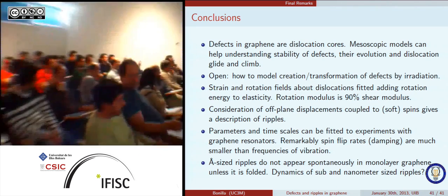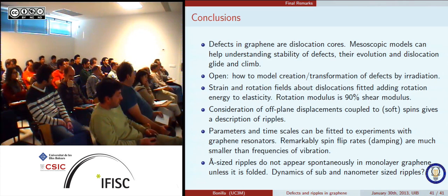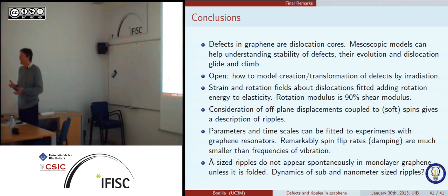You don't know the classical elastic systems in which this rotation is... No, because, okay, wait a minute, I take it back. If you have a liquid crystal or something like that, then these directors, as you probably know, cause the stress tensor to be antisymmetric. The symmetry of the stress tensor is just a question of balance of angular momentum. So if you have another source of angular momentum like that, then typically you get this antisymmetric stress, and then you get some cost to the rotation. But in classical elasticity, when you average, you use this balance of angular momentum and get rid of the rotation. Of course, these are crystals, so you should not average away structure.